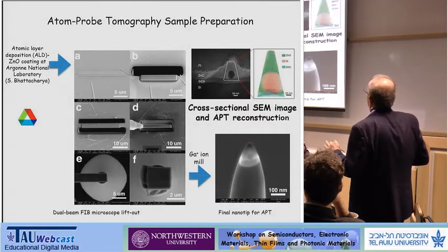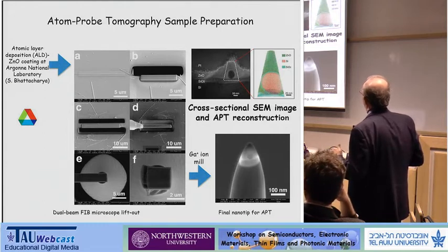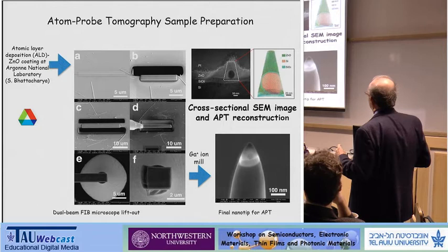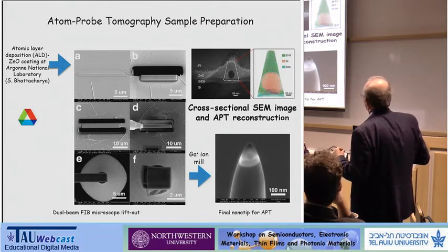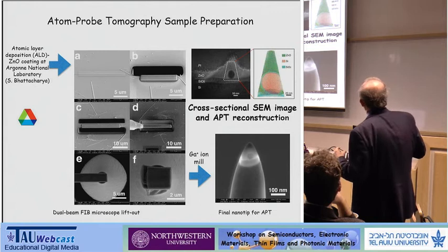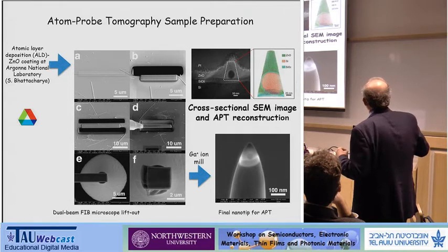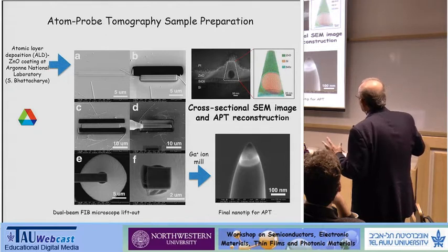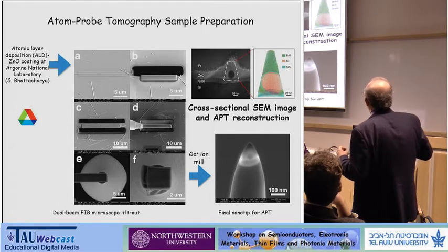Okay, once again, the real game changer here for us has been using the dual beam FIB. In this case, let me just show you the bottom line first on the right-hand side. So if you look here, this is a cross-sectional SEM image. And here you can see this horizontal nanowire, and this is the region. And you see it's sitting on silicon. And then you have silicon dioxide over here, maybe about 4 nanometers thick. And then you have zinc oxide, which turned out to be important. And that was done by atomic layer deposition. And then on top of that, we deposited platinum.